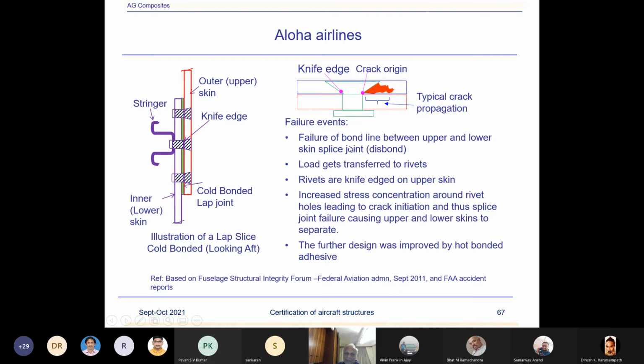So failure events: failure of bond line between upper and lower skin splices. This bond load gets transferred to the rivets. Rivets are knife edged on the upper skin. Increased stress concentration around rivet holes, leading to crack initiation and thus splice joint failure, causing upper and lower skins to separate. The further design was improved by hot bonded adhesive.